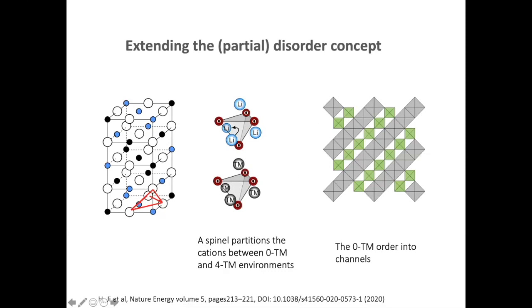This is actually spinel. If you look at a spinel, and I've here drawn an unusual setting of spinel, if you look at the tetrahedral environment in a spinel, they are perfectly segregated between pure lithium, so 0 TM, and 4 TM. And that's perfect. In a layered material, they are 1 TM and 3 TM segregated, which is also quite good. And so in a spinel, you already have these environments pre-made, and they actually form these connecting pathways, which are the tunnels in spinel. And so spinel indeed is a very good lithium diffuser.